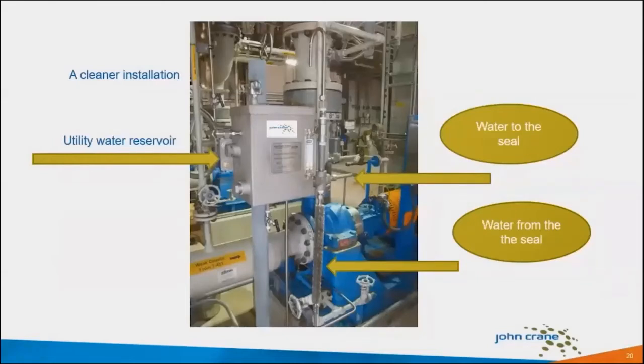This system can also be delivered as a pressurized system. So where we encounter much higher pressures, we can pressurize that water up to whatever is required, up to probably about 100 psi, if we're pumping against a very, very high pressure. But the system addresses, I think, the most common problem in mining applications, and that's seal face lubrication and wear.